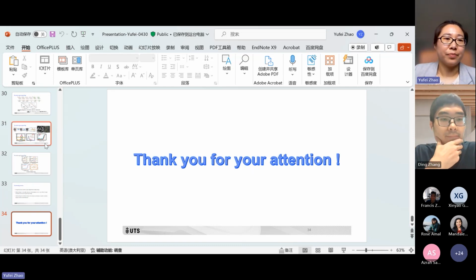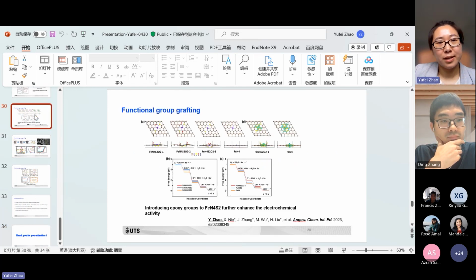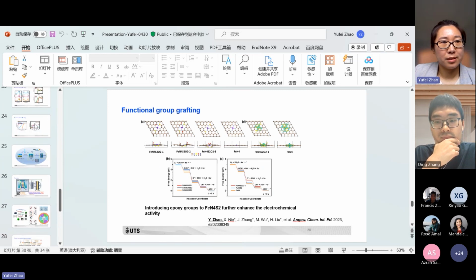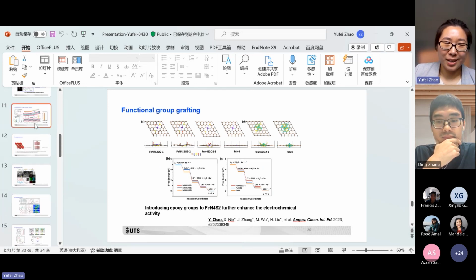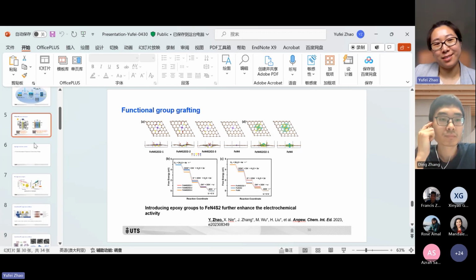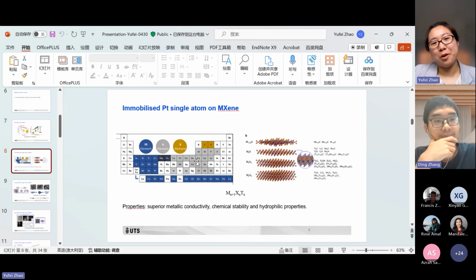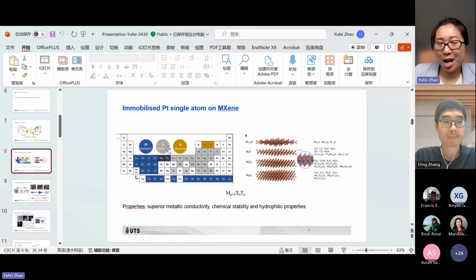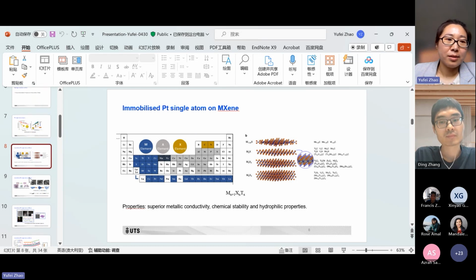I think that depends on the different conditions. For MXene, let me go back to MXene. For the MXene, it's quite stable, especially in acidic conditions. We know acidic is quite corrosive, but for MXene, from how to make the MXene, we need to etch the element out from the MAX phase. So for the MXene, it's extremely stable in acidic conditions. But for how to scale up the MXene, I think compared to the carbon material, it is not that promising. But for the stability, I think MXene may be better than the carbon material. And for the